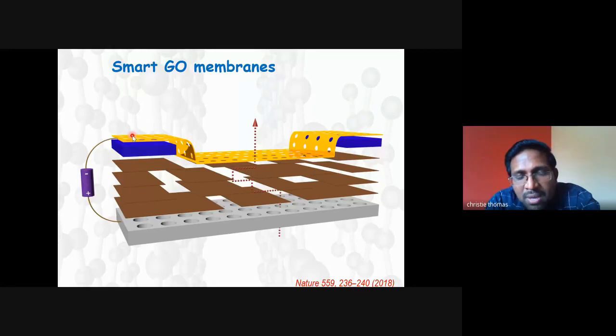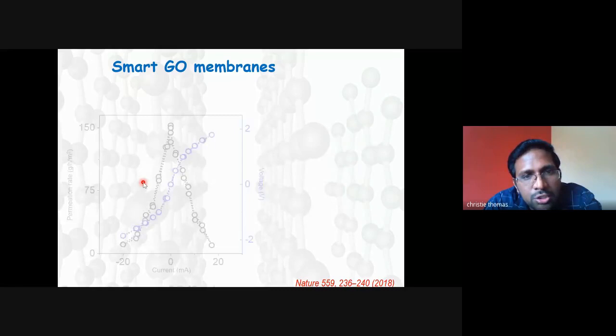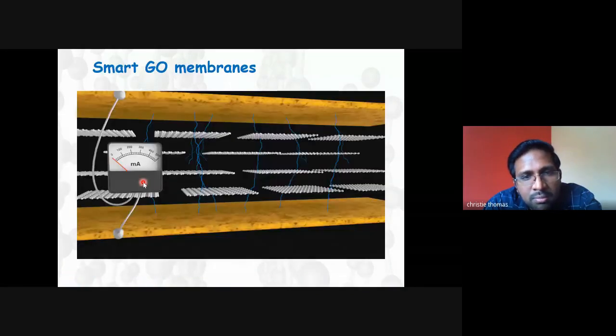So here is a schematic representation of our setup where you can see the graphene oxide membrane, and it has been coated on both sides with electrodes. One side is gold and the other side is silver, so that we can apply an electric field across it. You know that graphene oxide is insulating, and these electrodes are porous. Why? Because I want to measure the water permeation when I apply the electric field. I will skip this, maybe this is better.